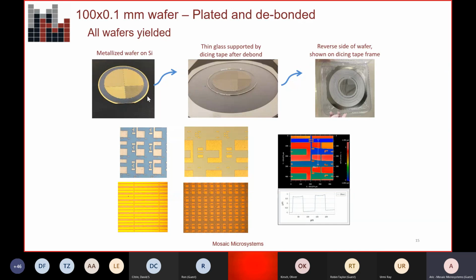So now I just want to step through some, I say that we can interface well with the supply chain. I just want to step through some examples of this, some things that we've done over the past couple of years. This first one is, it turns out it was a photonic application, but the customer wanted 100 micron thick glass with a 1.8 or 1.7 micron thick nickel gold structure, 4 structures, so it was a multi-project wafer, and down to about a 6 micron feature size. And so we worked with Micros in Raleigh-Durham for this, and this was one of our early processes.